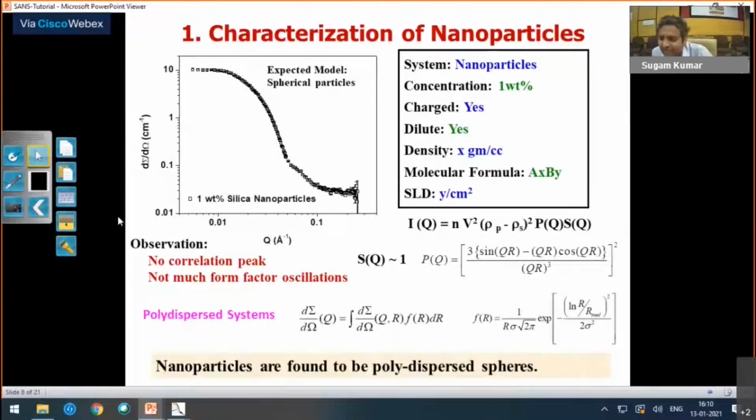So the question is, how do we know if the values of R polar and R equatorial are already known? Not always, but in case of, for example, micelles, what I have said is you have to make a clever guess of the initial values. In case of, let's say, SDS surfactant, I know the tail, the hydrophobic chain, is carbon 12.